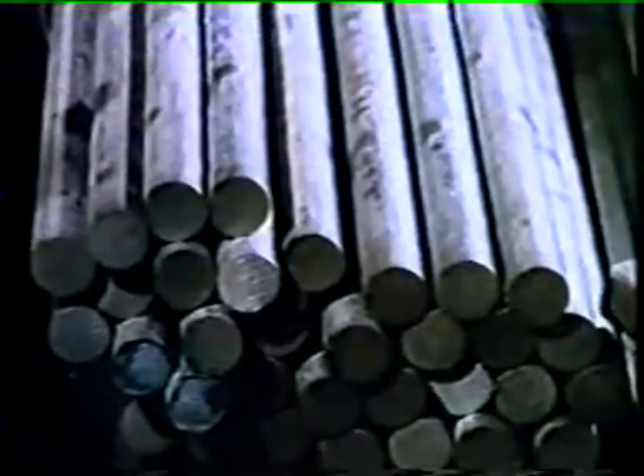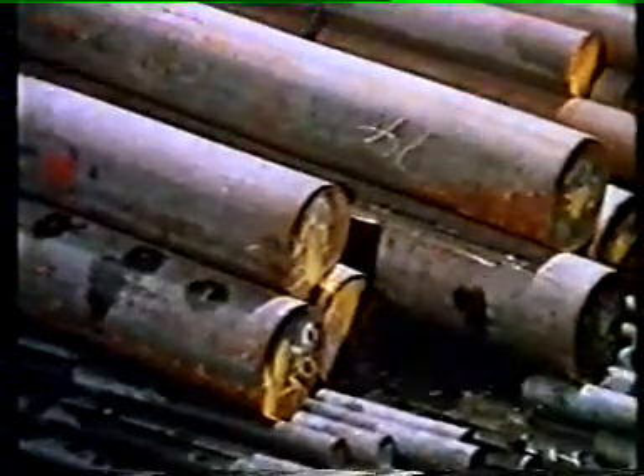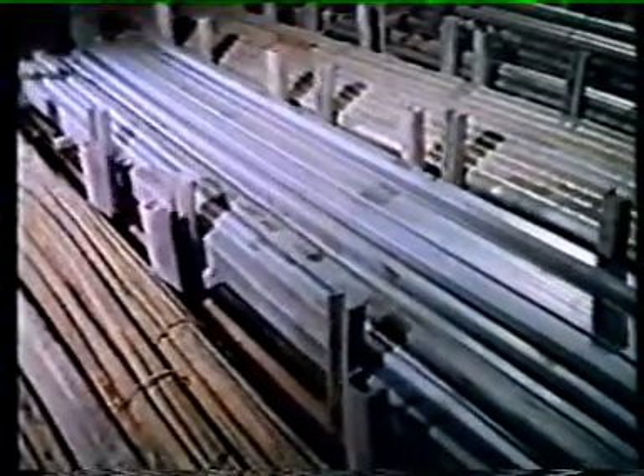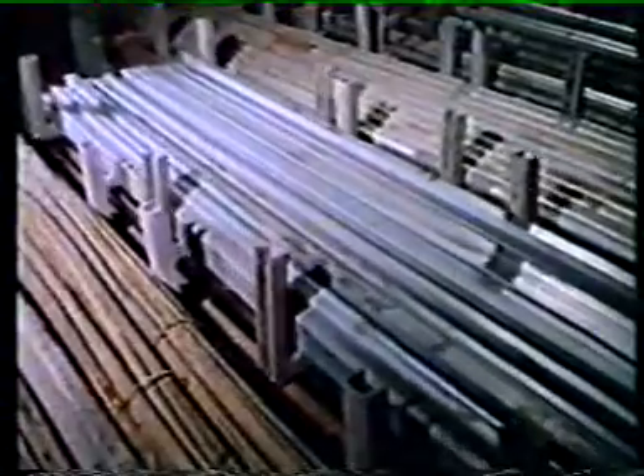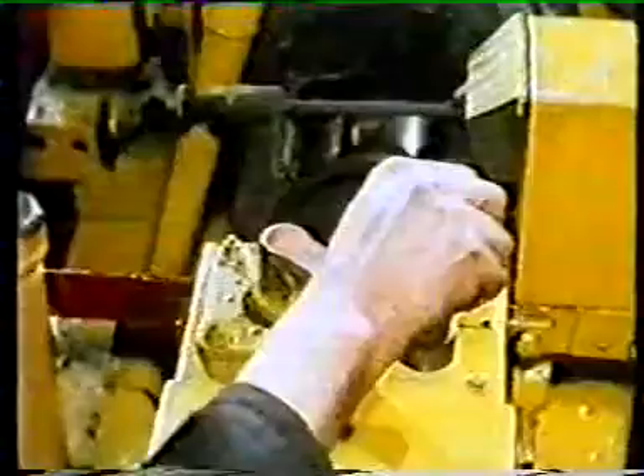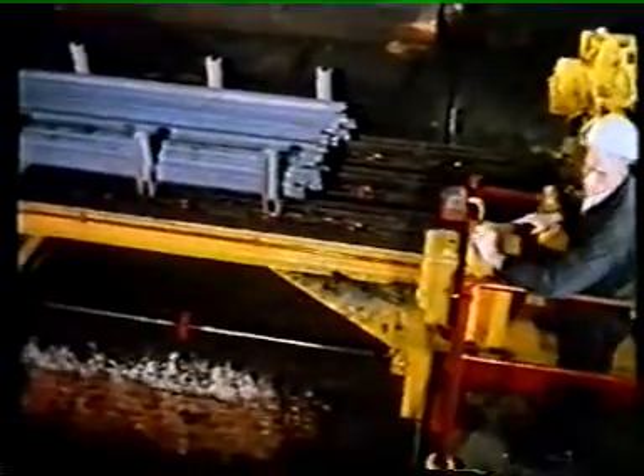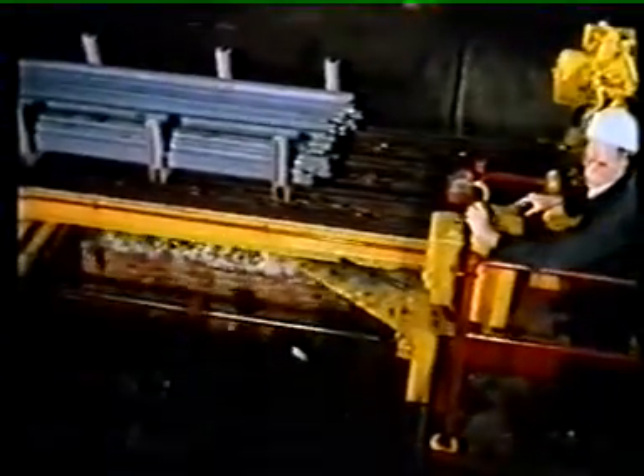Some customers want their rolled steel hardened and tempered before it reaches them, and these consignments are transferred to the heat treatment shop. In this shop, steel is treated in large batches, weighing from 35 to 50 hundredweights at a time. The first step is to heat the steel in a furnace so that the pearlitic structure is changed back to austenite, the reverse of what we saw in the diagram. The batch is left in the furnace for sufficient time for the heat to transform the structure of the steel right through.